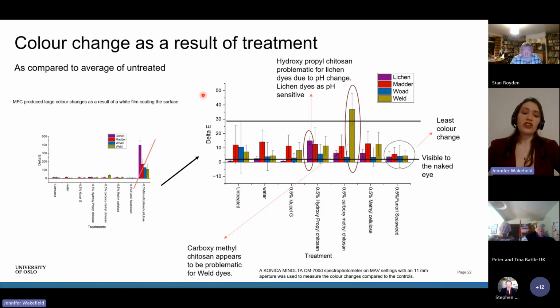Then we also looked at the color change. The microfibrillated cellulose was a complete disaster. It produced a white layer over the surface of the material. In cases where it was for paper, that wasn't so much of an issue, as that was opaque. But in terms of the woolen textiles, you want it to be completely see-through. So that was very much a problem, for all the dyes. When we don't include that, we can zoom in a little bit more on the rest of these. And we can see there's a lot of variability in here.